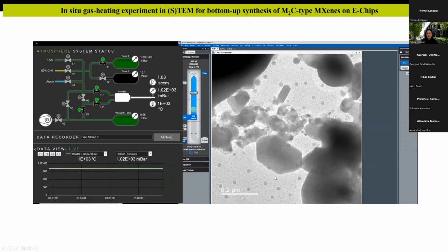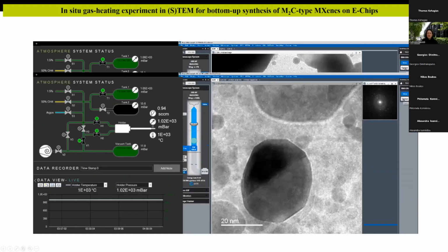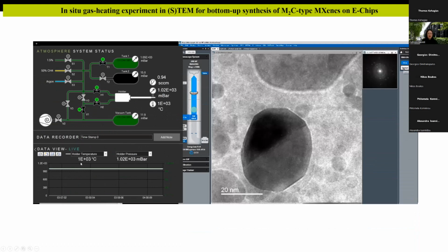Also, what is important to see is that even at the highest temperature, at 1000 degrees, the system is quite stable, so we could also acquire high-resolution images. Here you can see that we can easily see the lattice fringes. You can see also the FFT of these nano-sized flakes.